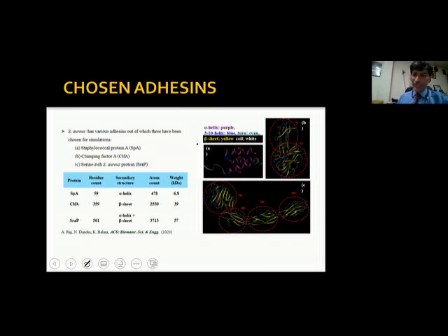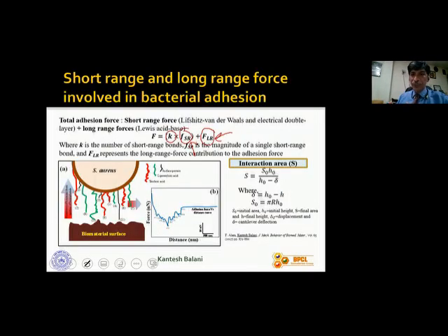Right? So short range are more towards whether the infection will spread further or not, and FLR is how strong that interaction is, right? I would have also highlighted this with one more slide, but I will just say it. Conventionally, if you want to see the adhesion, we go with something called a direct contact test or agar diffusion test. From that assessment, we will observe that the maximum number of dead cells are in ceramic hydroxyapatite. So conventionally, I would choose only ceramic. But here I am seeing that the least forces are in polymer. So this finding disproved the conventional knowledge; the minimal adhesion force is in polymer and not in ceramic. Conventionally we would have chosen hydroxyapatite, but actually it is polymer, which is easier to disinfect.